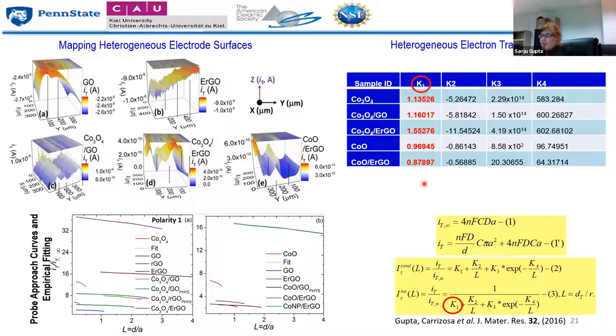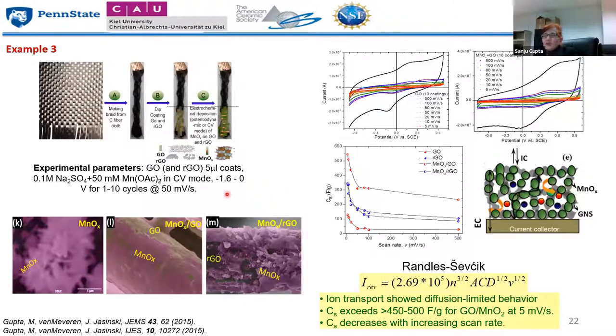So these engineered electrochemical electrodes start to provide us with which material would be the ideal if we want to really implement it at an industrial level. So as you can see here, Co3O4 on electrochemically reduced graphene oxide shows the highest K1, followed by some of these like Co3O4 on GO and so forth. Then in the third example, we combine with the manganese oxide, and we have compared both electrochemically deposited manganese oxide as well as the physisorption manganese oxide. And interestingly enough, our capacity for the manganese oxide on graphene oxide exceeded almost 550 at 5 millivolt per second. And this was the equation that I was talking about when you plot the current versus square root of scan rate, it provided us the diffusion limited behavior and so forth.